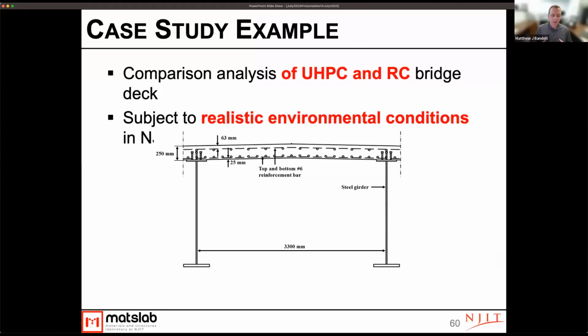And so what we did is we took a representative bridge deck, and we made comparisons of a bridge deck that was made of traditional reinforced concrete materials and made of UHPC. And when we did this, we took in mechanical properties and durability properties as our input parameters that were found from experimental testing that we did, in some of the results that Matt showed. But what we were able to do is simulate it over a much longer time frame than what we could simulate in our laboratory conditions. And we tried to subject that to realistic environmental conditions in New Jersey.